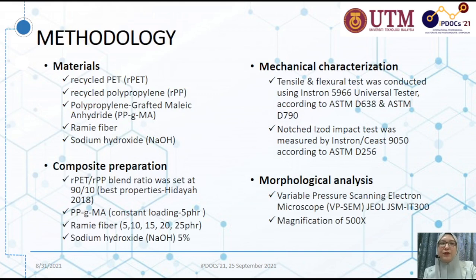Next is methodology. So the material we use in this research is recycled PET, recycled PP in the form of flakes. The compatibilizer we use is PPGMA. The fiber we use is Ramie fiber that was obtained from Wonosobo, Jawa Tengah, Indonesia. To treat the Ramie fiber, we use sodium hydroxide.